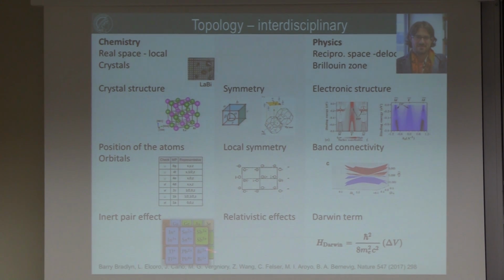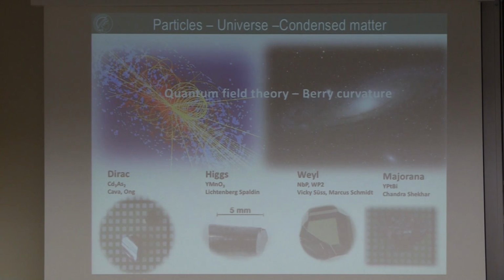And this is very often the so-called band inversion. Responsible for the band inversion in the topological materials is the sp inversion due to the 6s electrons. So you can predict more or less all the materials having this valence, and more or less all the heavy materials have some topology. There are some additional conditions to make them interesting topological insulators. They should be insulating, they should have only an odd number of band inversions, etc. But I think these are already very good rules, and they are summarized in this paper which we published together with Andrei Bernevig.